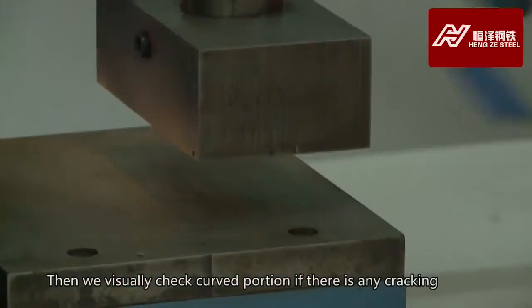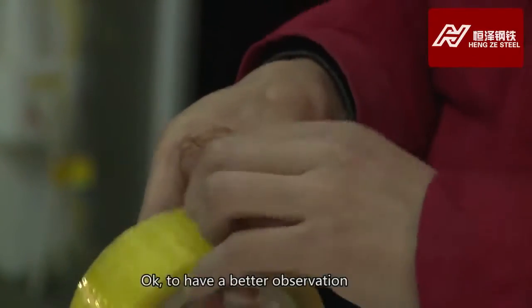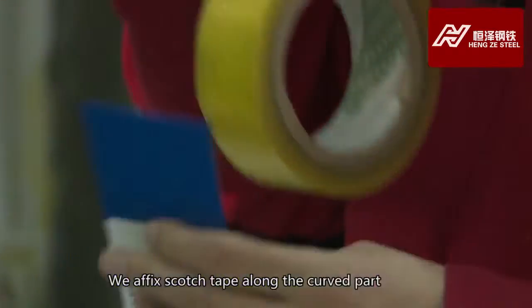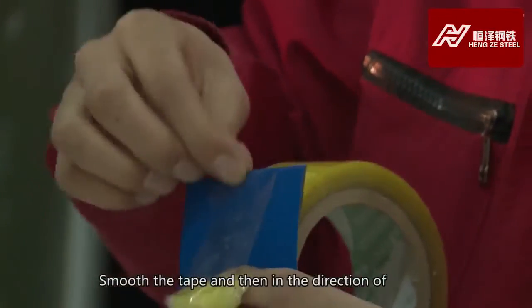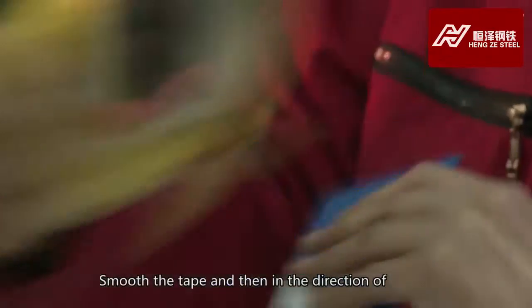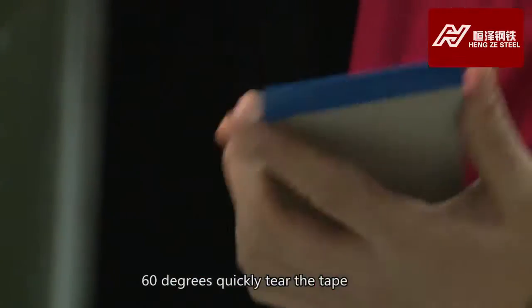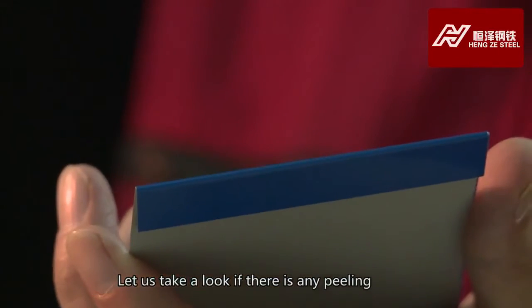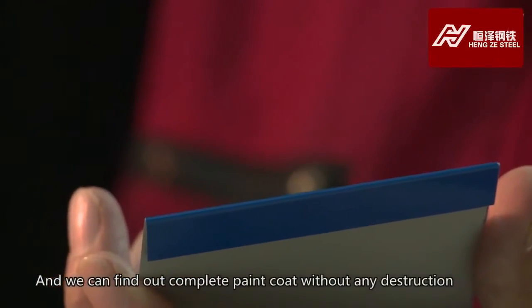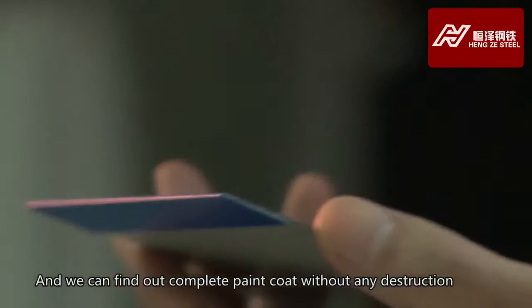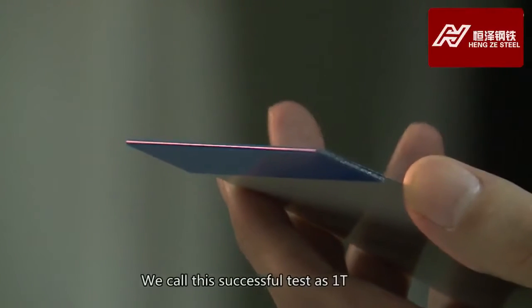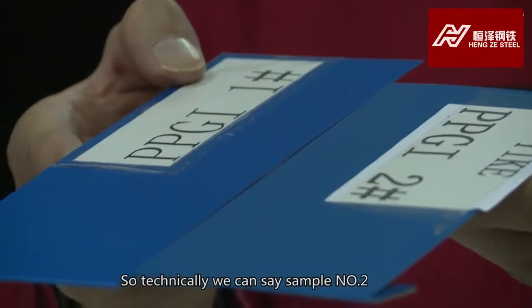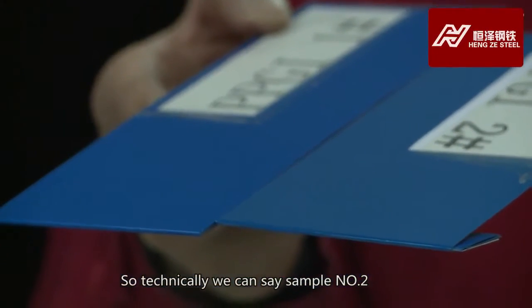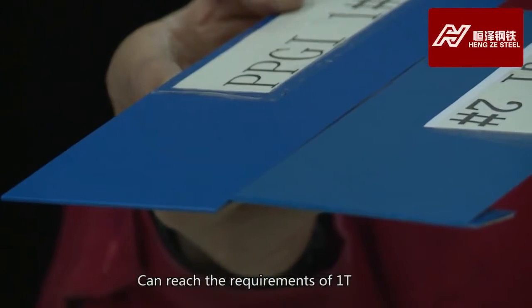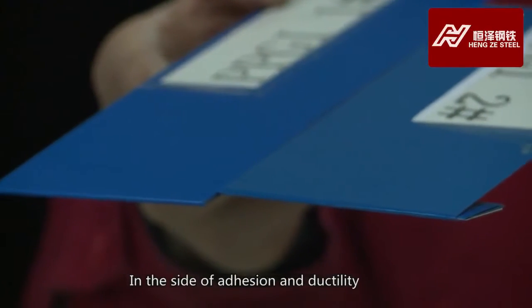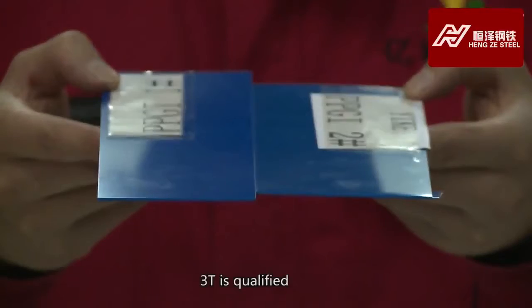Then we visually check the curved portion. To have a better observation, we affix Scotch tape along the curved part, smooth the tape, and then quickly tear the tape in the direction of 60 degrees. Let us take a look if there is any peeling, and we find a complete paint coat without any destruction. We call this successful test 1T. So, technically, we can say sample number 2 can reach the requirements of 1T in terms of adhesion and ductility. 3T is qualified.